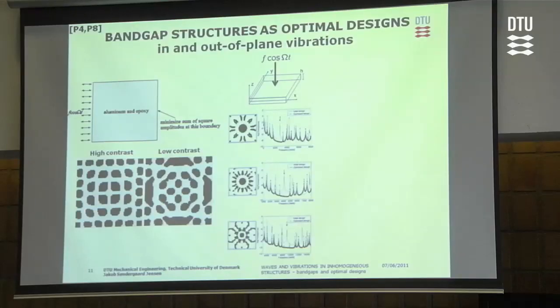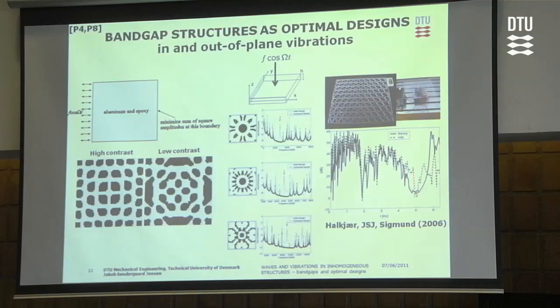We later extended the work to include out-of-plane bending vibrations, and found that a similar study yielded periodic-like structures for the distribution of two materials to minimize vibration levels. We did experiments for a band gap structure for out-of-plane bending vibrations and saw good agreement between experiments and theory.